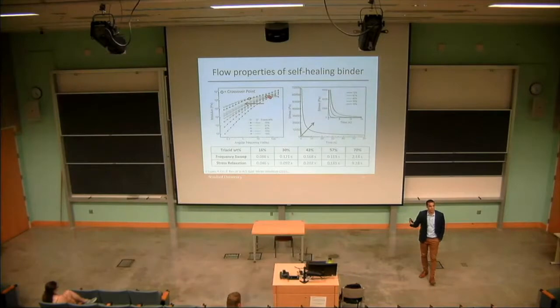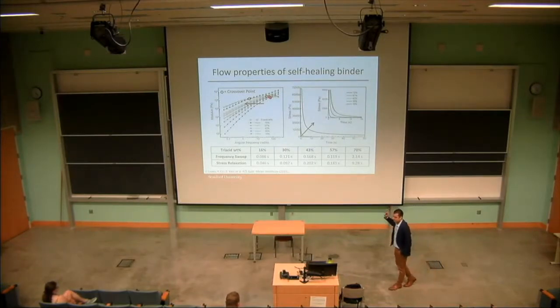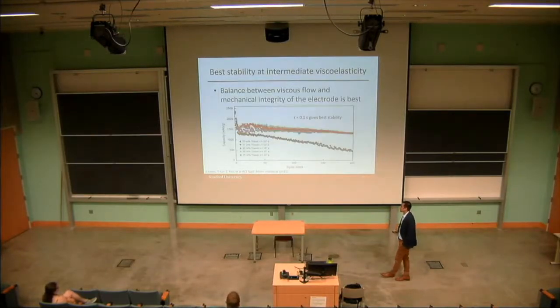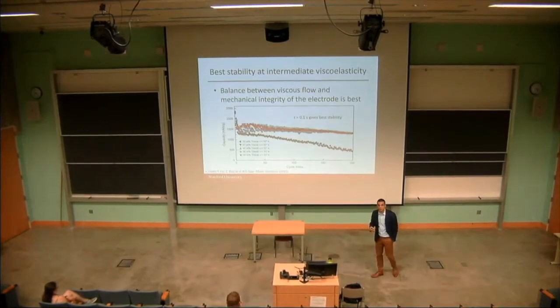So we really have successfully found a study that gives us very different mechanical properties without changing the chemistry at all. And so then jumping right back into the cycling curves, again, this is capacity or charge stored per weight of silicon versus cycle. You can see very quickly that the most cross-linked material, the most solid-like material, has very poor performance. And then if you look a little bit more closely into the data, what you'll find is that relaxation times on the order of about 0.1 second give us the best cycling stability.